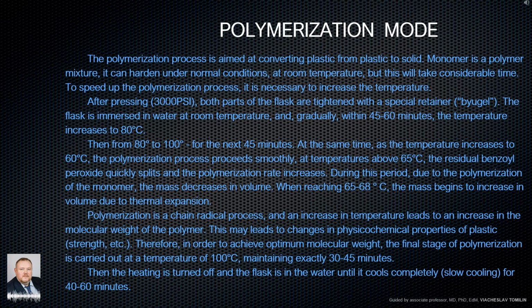Polymerization is a chain radical process, and an increase in temperature leads to an increase in the molecular weight of the polymer. This may lead to changes in physicochemical properties of plastic, strength, etc. Therefore, in order to achieve optimum molecular weight, the final stage of polymerization is carried out at a temperature of 100 degrees Celsius, maintaining exactly 30 to 45 minutes. Then the heating is turned off and the flask stays in the water until it cools completely, slow cooling, for 40 to 60 minutes.